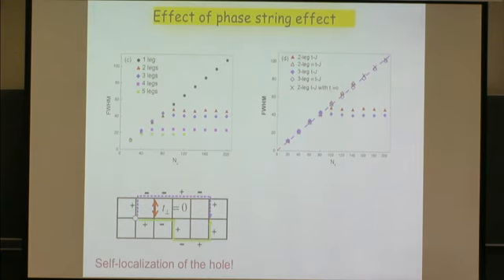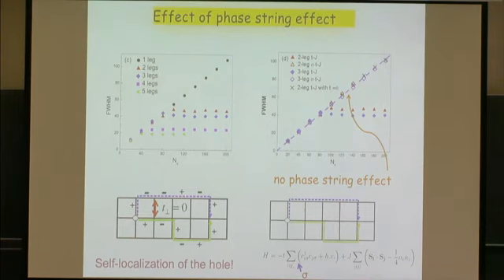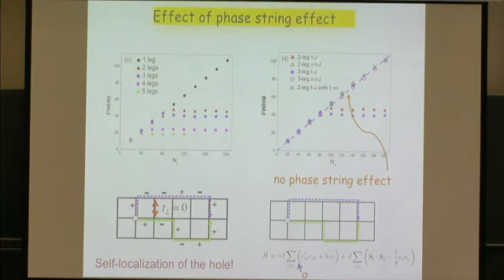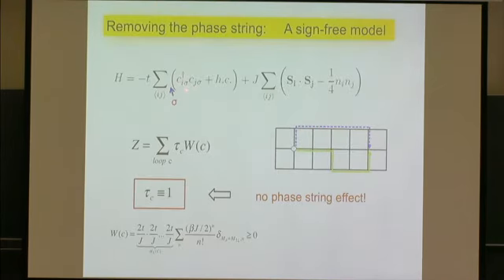They become extended. Another probe is that you can switch off this sign structure by putting sigma in this hopping term. Then there's no sign structure here, and you find that the 2-leg and 3-leg cases go back to the extended profile. In this model, sigma is just up and down, taking the value plus or minus, which precisely cancels out the sign structure we see. Therefore tau c is 1, and W_c is the same as before. So we have two models. You can turn on this sign, turn off this sign, and do numerical simulation.